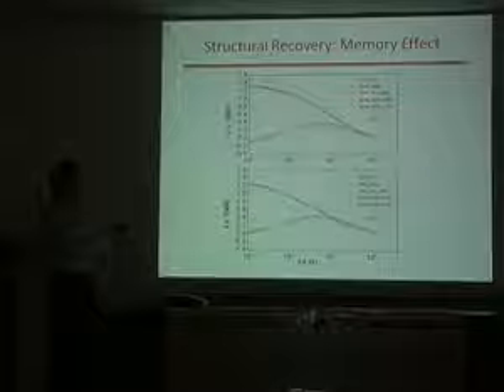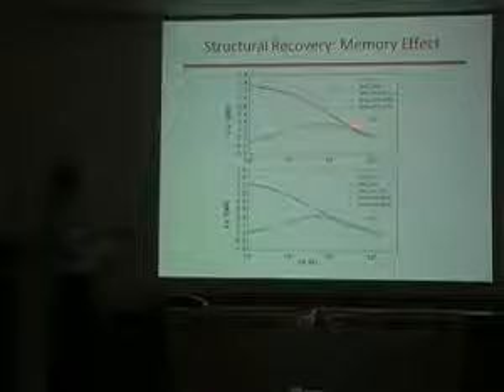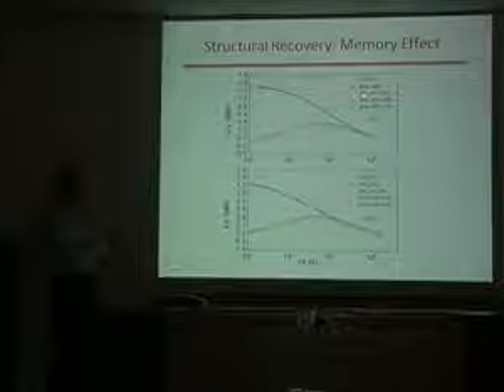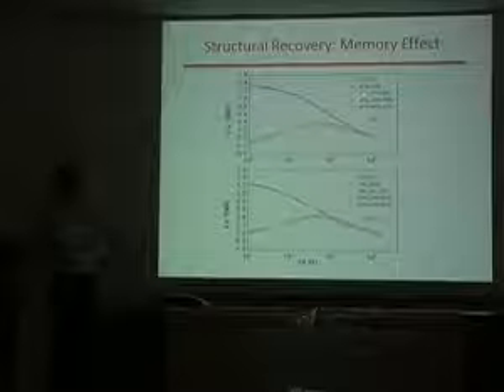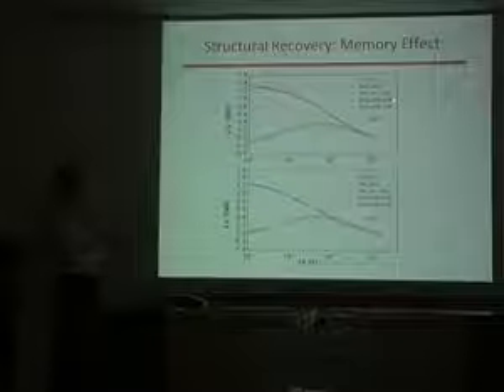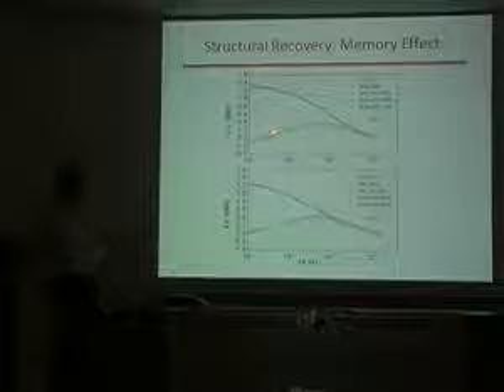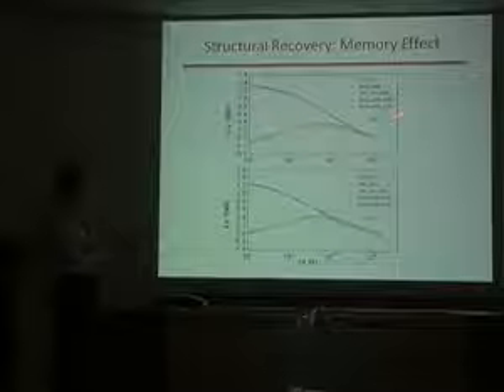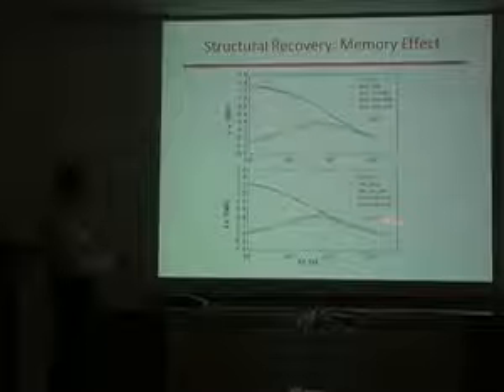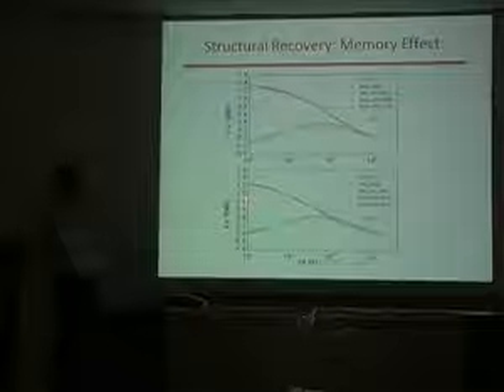When I do the partial structural recovery, so this is the direct jump to 50% from 90% relative humidity. Then I do this two-step from the initial relative humidity of 90% down to 30%, let it age for some time, and then jump back up to 50%. I find that I get this curve. And when I do it at 40%, I get this curve. And when I change temperatures, I get qualitatively the same thing, the same kind of response. So I get the memory effect.